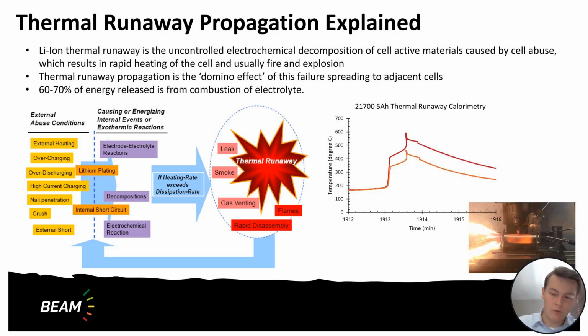What is thermal runaway propagation? Well, the propagation aspect is when that failure spreads to neighboring cells like a domino effect. And that's caused by the heat coming from that failing cell spreading and overheating surrounding cells. So heat and the thermal distribution is a major problem, and obviously a key topic of today's discussion. But I also want to make mention that you can get electrical shorting problems that occur through battery packs during a thermal runaway event, and that can also lead to internal heating or current dumping from neighboring cells as they're experiencing external short circuiting, which is obviously a root cause of thermal runaway in those cells as well. So you need to deal with the thermal problems as well as the electrical problems.